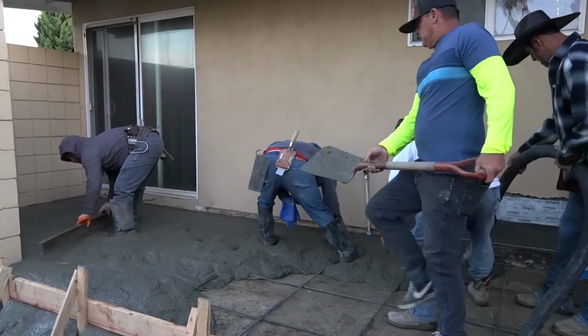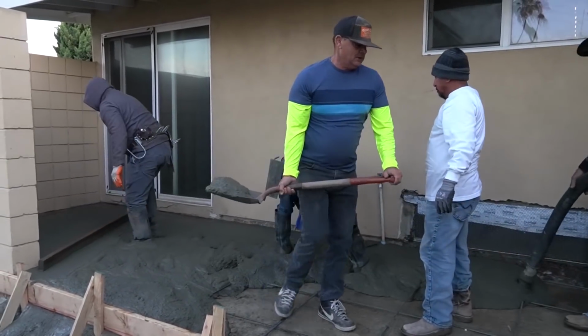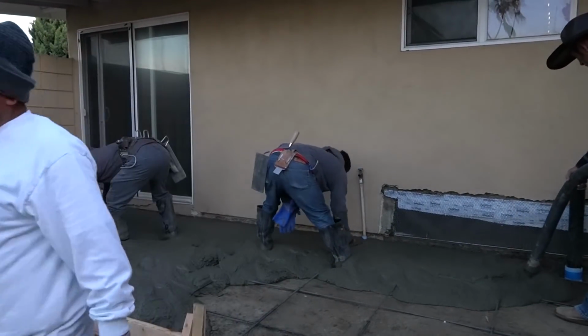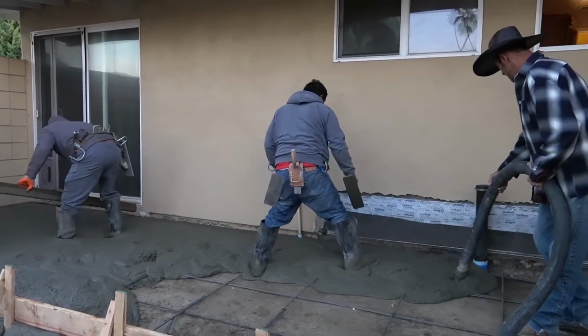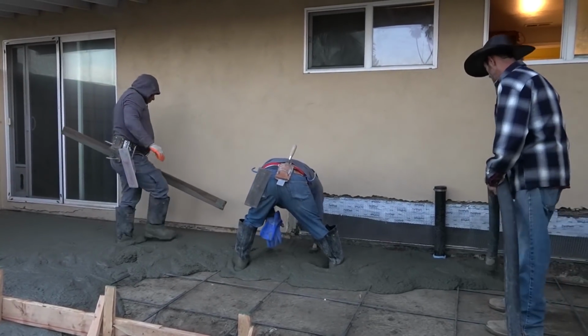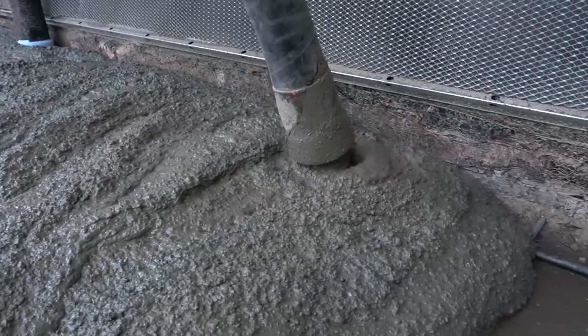We're just pulling the steel up by hand. You want it in the bottom third. It's just to hold it together with tensile as one piece. And there's microfiber. I go with the City Mix in the winter, a 3250. I use it the whole winter. It's a straight sack, no fly ash mix. In the summer, I use a 3000 straight sack. But I'll use the City Mix, and sometimes I'll throw Polar Set or accelerants in it.